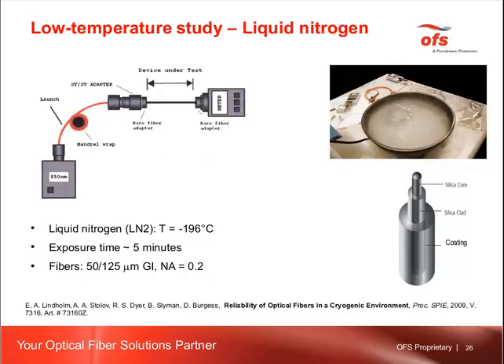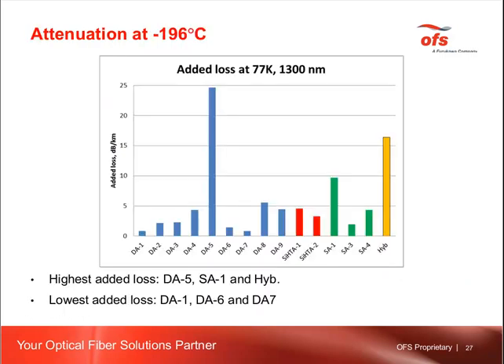Low temperature properties of the fibers. A fiber coil can be immersed in liquid nitrogen. Then, due to a mismatch between the CTEs of the coating and the glass, we expect seeing microbends. Then, if we have this fiber in line with the optical measurement bench, we can register added optical loss due to these microbends developed at low temperature. These results are shown on this diagram.